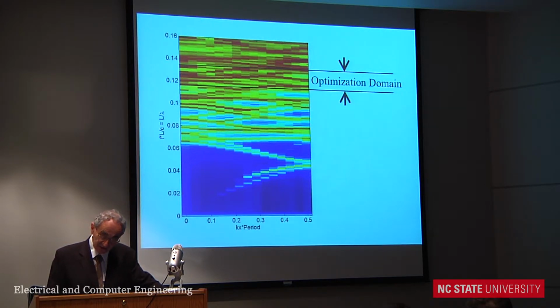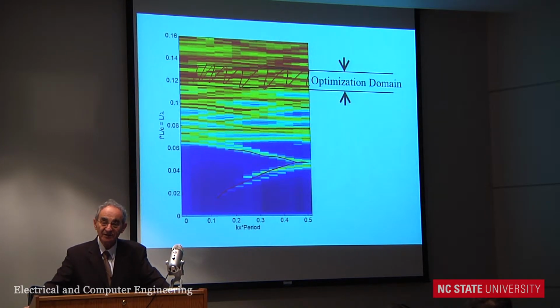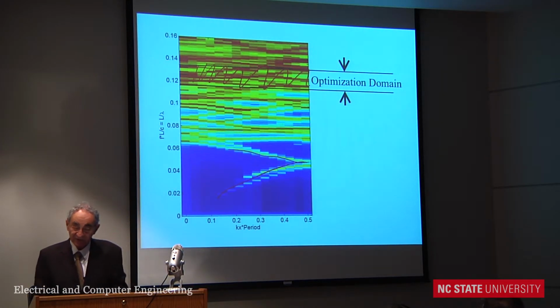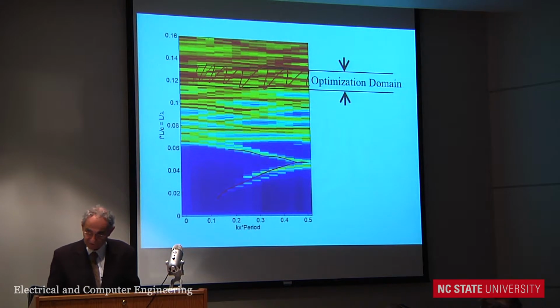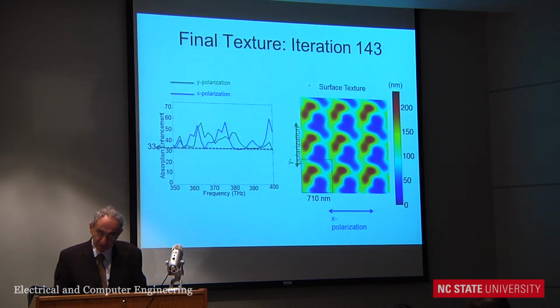But where you get the best performance is in the band structure. You have stuff down here, normal band structure, but the place where the solar cell wants to be is in the higher bands, where you have many bands, and we call it the spaghetti region of the band structure. You have many bands going all over the place. That turns out to be the best place to put the weakly absorbing parts of the solar spectrum. And she ends up with the final performance. It ends up with weird shapes like this.